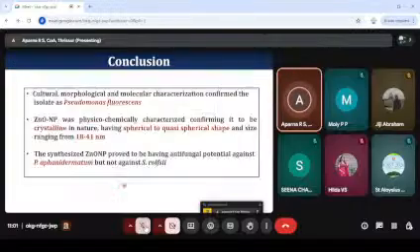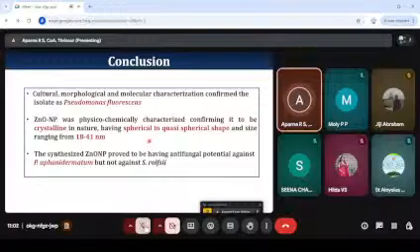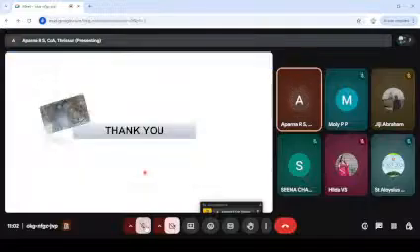So the conclusion is that the Pseudomonas fluorescens isolate was culturally, morphologically and molecularly characterized, and this was used for the zinc oxide nanoparticle synthesis, which was further physicochemically characterized, confirming its crystalline nature, spherical to quasi-spherical shape, and size was found to be in the range of 18 to 41 nanometer. And when it was subjected to test its efficacy against several fungal pathogens, it was found to have potential in inhibiting Pythium aphanidermatum, but not against Sclerotium rolfsii. Thank you.